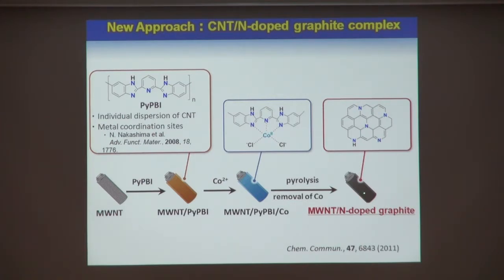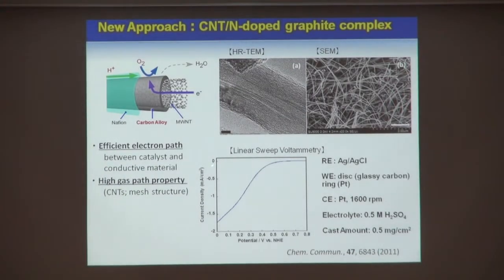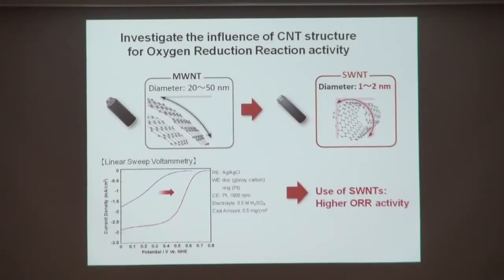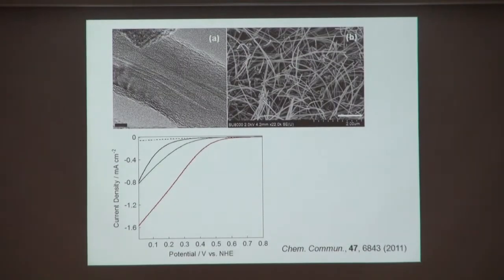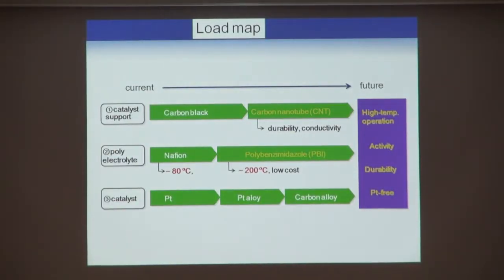And we found that this catalyst acts as an ORR, oxygen reduction catalyst without the presence of platinum like this. But compared to platinum catalyst, performance at this moment is not very high. But in this case, we use multiple carbon nanotube. When we use a single carbon nanotube, performance improved like this. But anyhow, compared to conventional platinum type, we need to improve the performance. Anyhow, it's important that the catalyst is without using any platinum, that's platinum free.